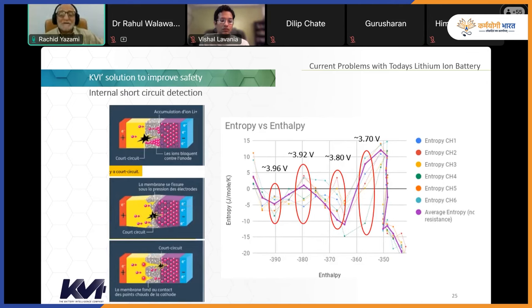Yes. So our approach here, this is our solution today, is to use the entropy of the battery as an internal short circuit detector. What happens is that, number one, the entropy of a battery can be measured very simply by measuring open circuit voltage and the temperature. If we measure OCV and the temperature very accurately, we can get the entropy, because basically the entropy is proportional to the temperature derivative of voltage.